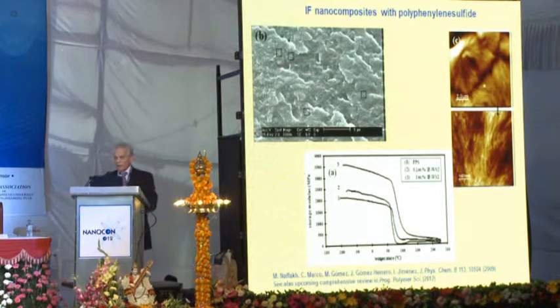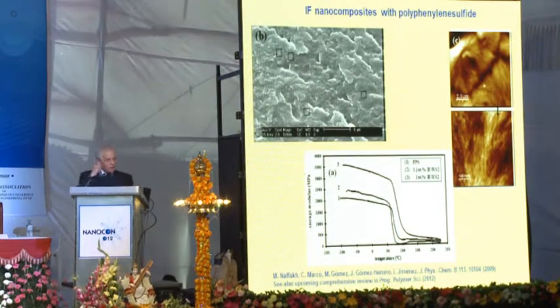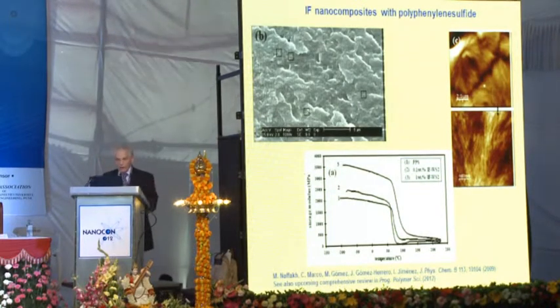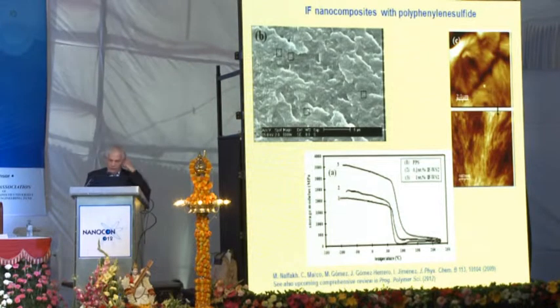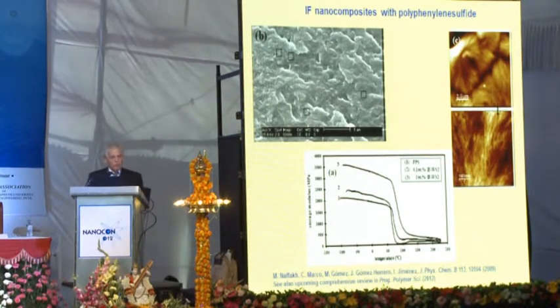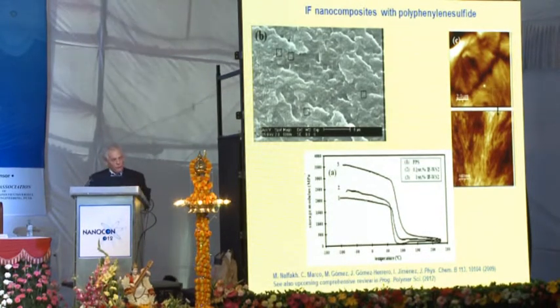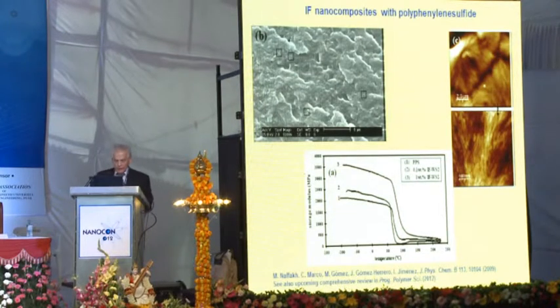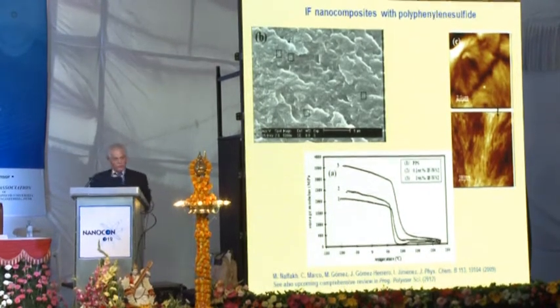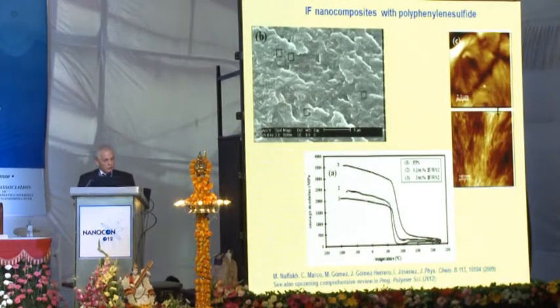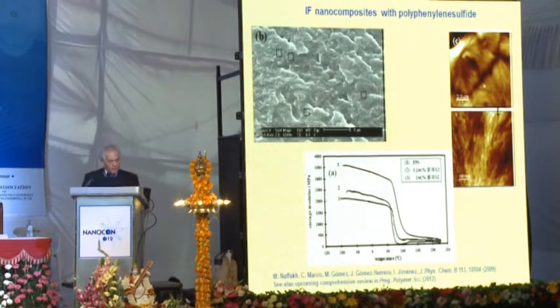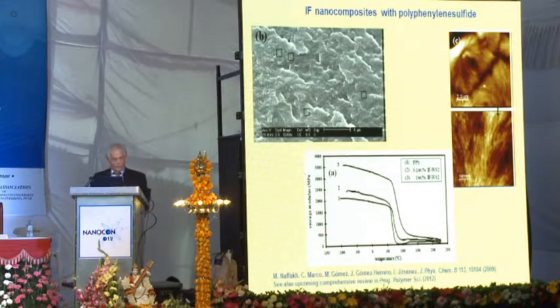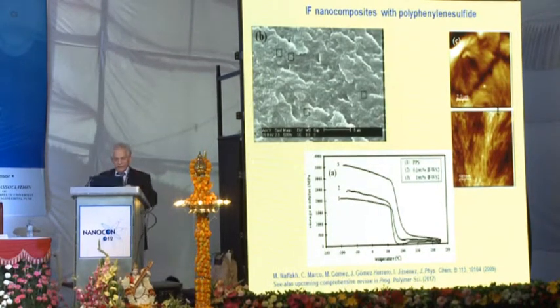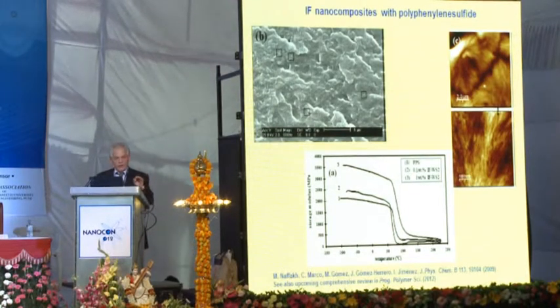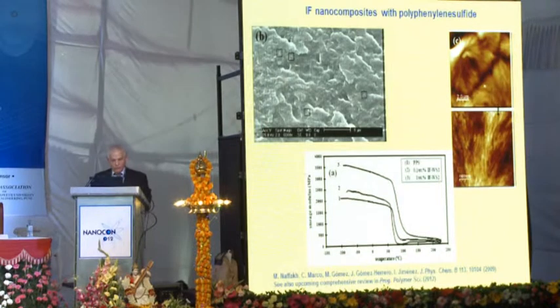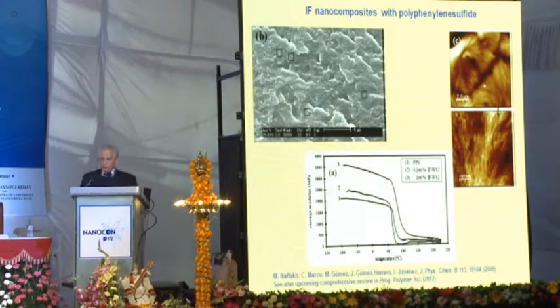Another very important recent application is in the field of nanocomposites. There is quite an important and extensive effort, mostly in Europe, to exploit these nanoparticles in reinforcing polymer nanocomposites. And I would like to mention especially two laboratories, the laboratory of Hannah Dodiuk in Shenkar College in Israel, and the laboratory of Mohammad Nafakh in Madrid. Muhammad did great work in demonstrating that by adding 1 to 2% of these nanoparticles into a variety of thermoplastic polymers, you can reinforce the structure of polymers dramatically.